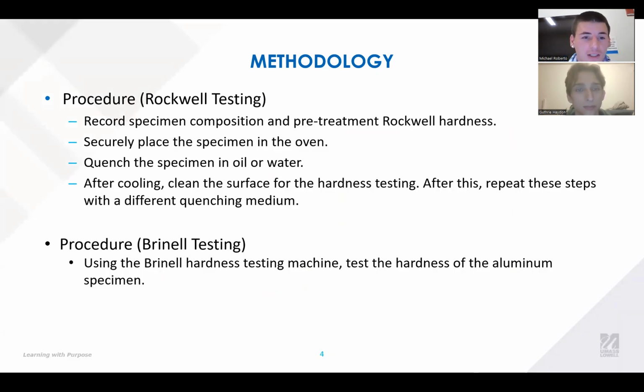For the procedure of the Rockwell hardness testing, we recorded the specimens' composition and pre-treatment Rockwell hardness, and we did this for all the specimens: the aluminum, brass, steel 1018, and steel 1045. The steel 1018 was placed in the oven and heated to roughly 840 degrees Celsius, which gave it a bright red color. Then we quenched the steel 1018 in oil or water. After it was cooled down, we cleaned the surface and tested its hardness using the Rockwell B and C testing. Then we repeated the steps of quenching the specimen. If we didn't do it before in oil, we did it in water and vice versa.